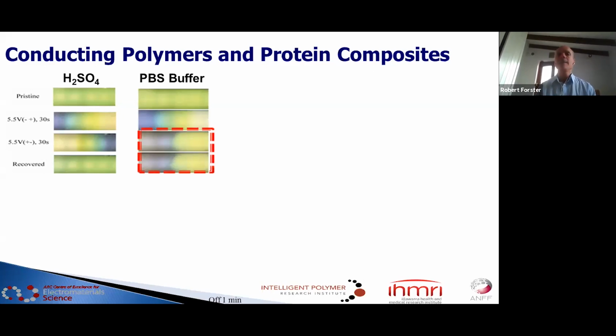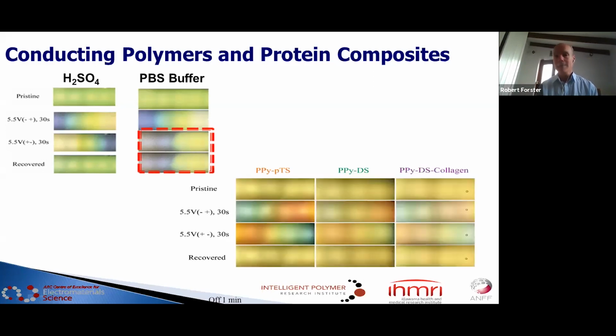Very interestingly, you can do this also in more complex, biocompatible buffers like PBS, and again induce this distribution of redox states across the PANI film within this bipolar electrochemical cell. More significantly, you can change the anion within the polypyrrole film to, for example, dextran sulfate, or you can even introduce proteins within that layer, for example collagen.